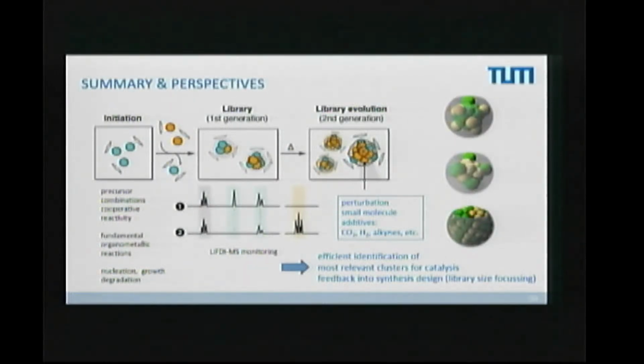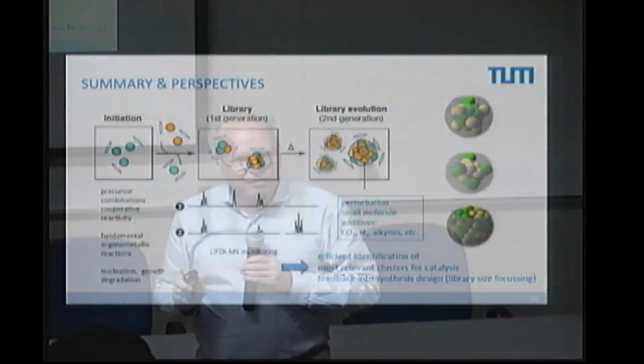The library generation and library evolution has two aspects. One is related to the generation and how the library, when we generate it, evolves over time. And when we add substrates like the alkyne, the hydrogen, or the CO2, we call it perturbation. This is basically we interfere with the intrinsic property of the cluster library if a chemistry is going on which is catalytic, and this may also interfere in a huge way in terms of reconstructing the more labile clusters which are pre-catalyst in this scenario. That is the goal, hunting for the labile ones which do the reconstruction connected to catalytic transformations. Thank you very much.